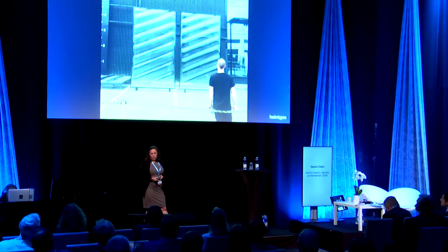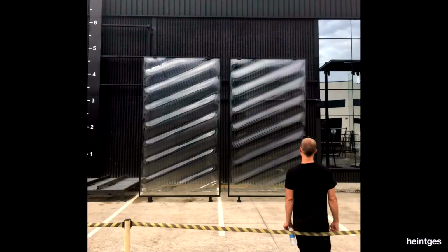And then we moved on to the next round of visual mock-ups, which were full-size, project-size IGUs that were reviewed at Precursor's plant by the design team to make the final decisions about the pattern and location of the microtexture, as well as the slump shape. At this point, we settled on the glass makeup. It's 10 plus 10. The outer light is carved, as I mentioned, with about 1 millimeter deep grooves, and they were 20 millimeters wide. And then the inner light is heat strengthened with a low E coating on the #5 surface.